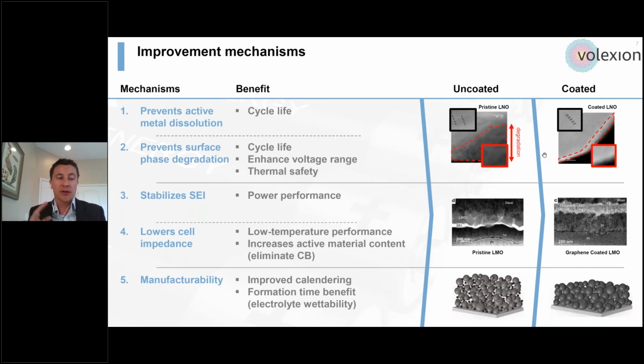The third large driver, and that's the 5th mechanism to improve performance of battery materials thanks to our graphene coating, is the ability to improve the process manufacturability of the cathode as an electrode, because we have the ability to remove carbon black from the electrode, which improves the calendaring and the ability to control the thickness of the electrode. And also our coating improves the wettability of the electrolyte, which drives benefit in terms of formation time.